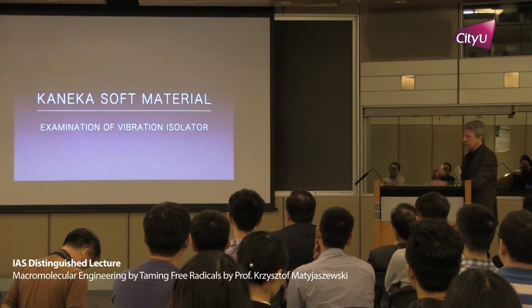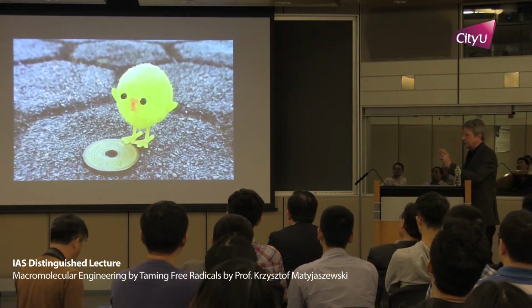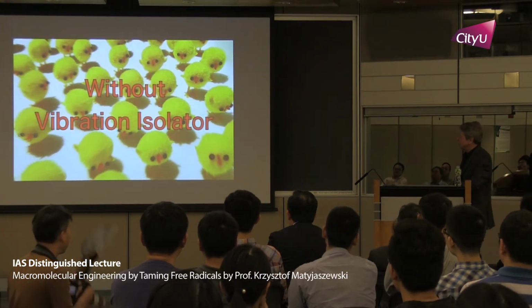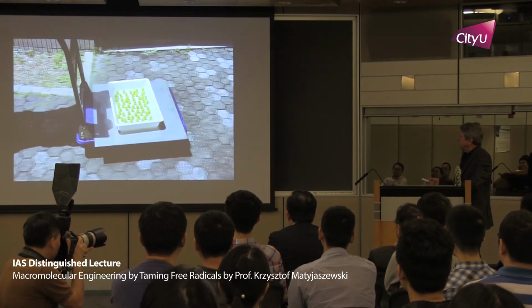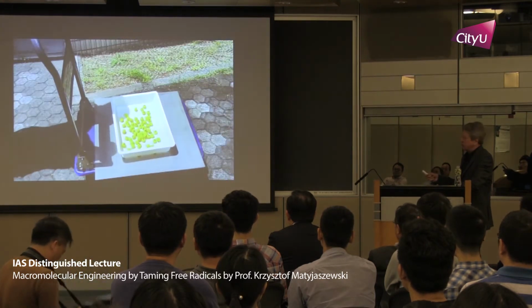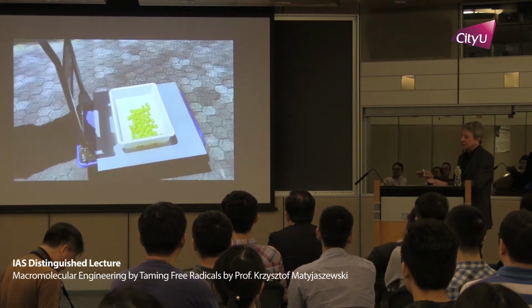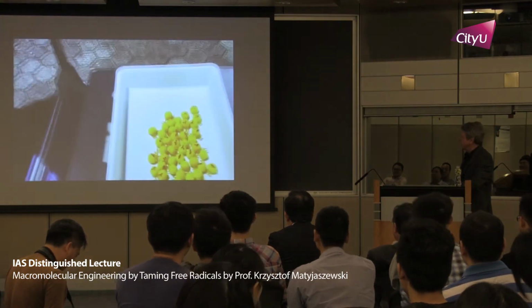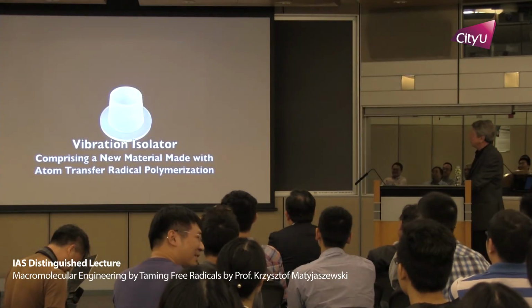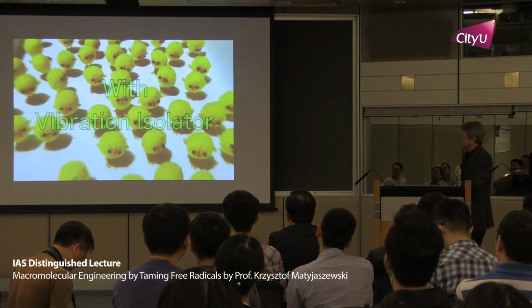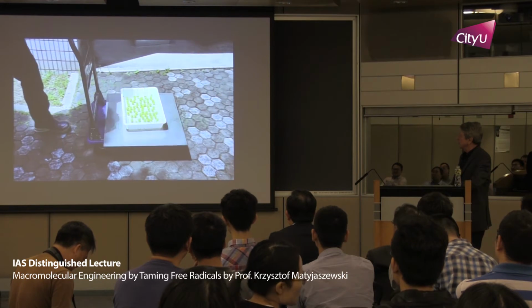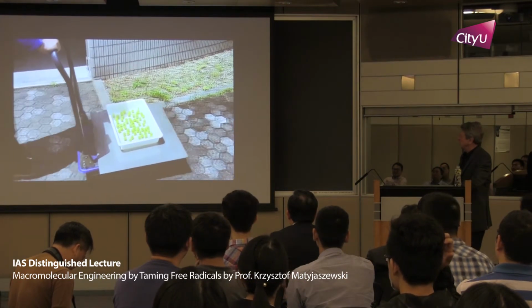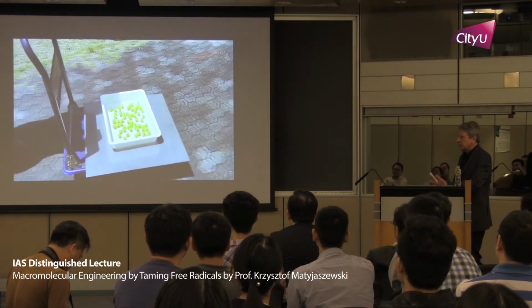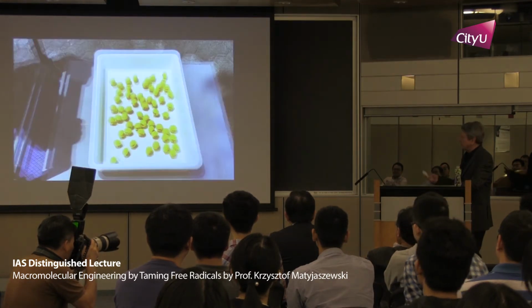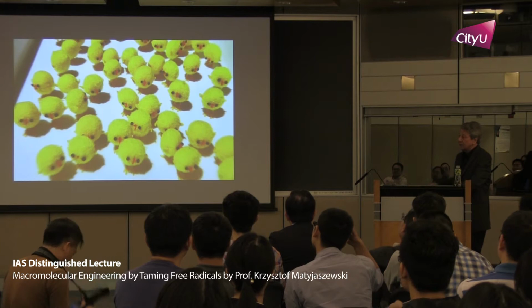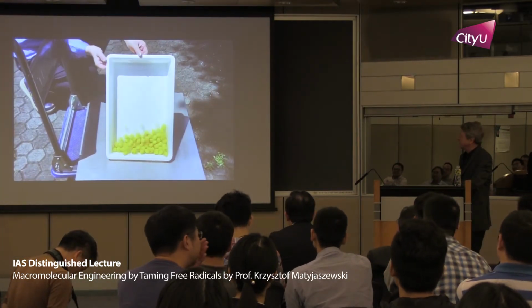There is also another less serious example. Small chickens in Japan, of the size of this 5 yen coin. You could see here what happens if you have no vibration isolator. All of these chickens are dead, essentially, after the 1 meter transportation. They don't look very bad. But if you look with the vibration isolator, it is a very different story, on the same surface, going more or less under the same conditions. So this vibration isolator absorbs all of the shock coming from the rough surface. And somebody told me that maybe somebody glued them to the bottom, but you will see in a moment that this was not the case.